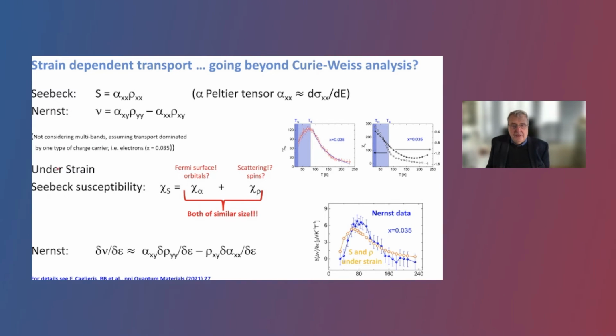And if you now have a strain, you can argue that you have two components for this Seebeck effect. A component which is a strain derivative related to the Peltier tensor, to the Fermi surface, if you want, in simple language, and a strain derivative which comes from the resistivity part. So this is what we measure by measuring the strain derivative of the resistivity. And the message is both are of similar size. The sign depends on the Fermi surface part for this one here, but both are of similar size. So you really have an additional quantity here besides the nematic susceptibility which we are used to from the resistivity. And this is also, of course, the reason why we have these different concentration dependencies.